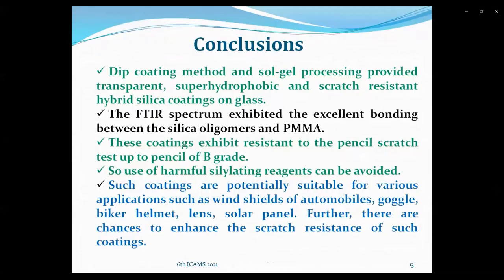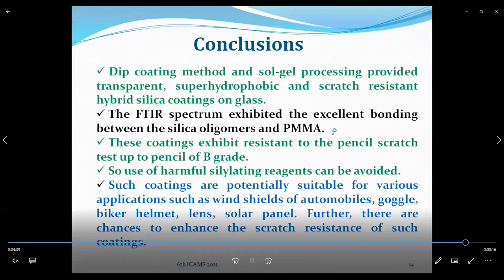The dip coating method and sol-gel processing provided transparent, superhydrophobic and scratch resistant silica coatings on glass. The FTIR spectrum exhibited excellent bonding between the silica oligomers and PMMA. These coatings exhibit resistance to the pencil scratch test up to pencil grade B. So the use of harmful silylating reagents can be avoided. Such coatings are potentially suitable for various applications.